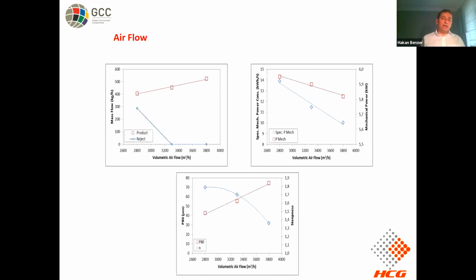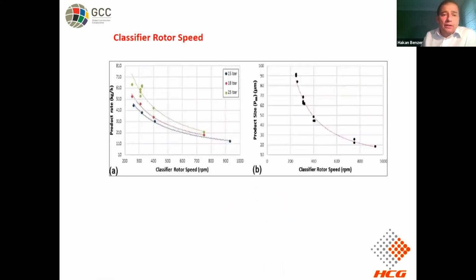At the same time, we focused on the airflow, and if you increase the volumetric airflow to the system, the mass flow from the system is increasing. You are getting more product, and the circulating load is reducing. Of course, the increased volumetric airflow ends up with a coarser product size, and the steepness is affected as well with the volumetric airflow because of the reduced bypass of the dynamic classifier. Of course, we are using a classifier rotor speed, and if you increase the classifier rotor speed, because of the centrifugal force increase, we are getting finer product from the system.